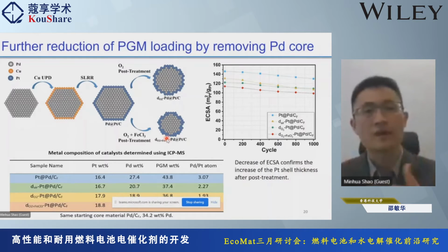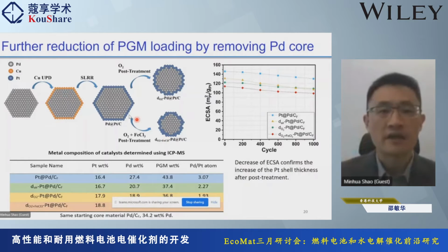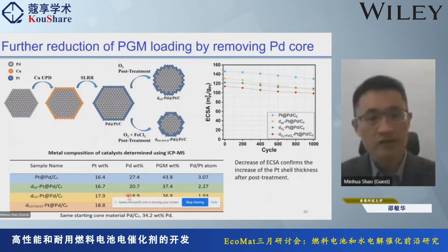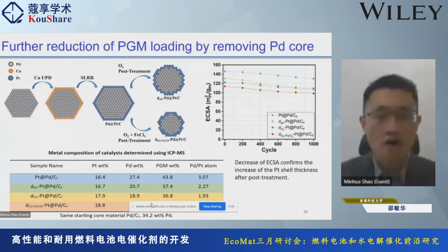Okay, so resulting in this redistribution of the platinum on the surface. So that means your platinum layer probably will be thicker than the original one. Okay, so originally probably 1 to 2 layers. After the post-treatment, the thickness of platinum grows to 2 to 3 layers, right? So that it can further protect your core shell structure. So we tried different methods for this post-treatment.